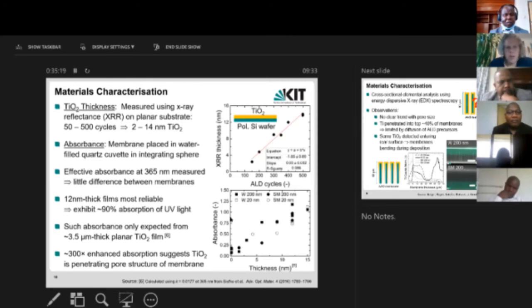And then, like I said before, this was all measured on a polished silicon wafer. When I'm talking about thickness, for example, in the bottom half of this graph, the thickness on the x-axis is the planar thickness, but of course the measured absorption here is effectively much greater because that is deposited inside this porous substrate. I should probably be a little bit clearer and call this a nominal thickness, because it's not the thickness as measured inside the membrane pores, it's the thickness on a polished silicon wafer. Apologies, it's a little bit misleading how I've presented it.